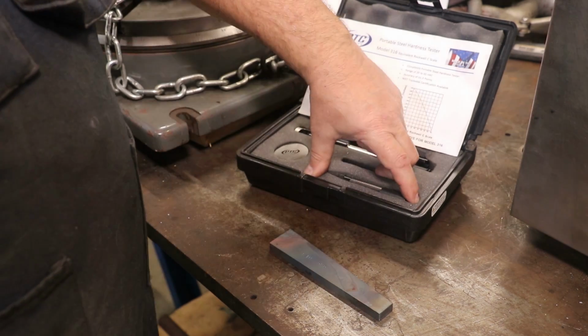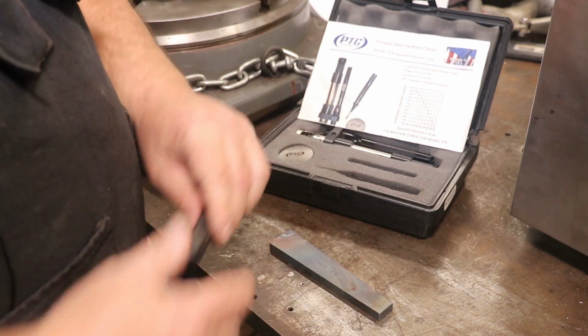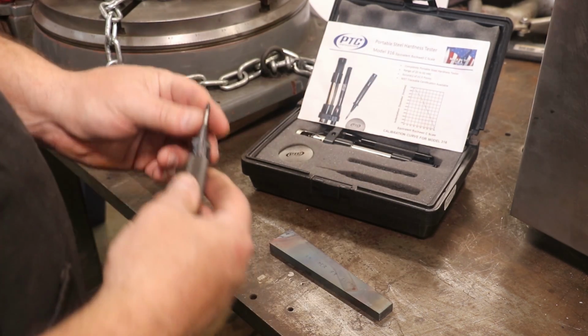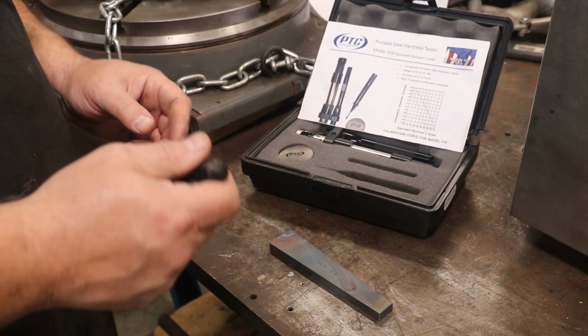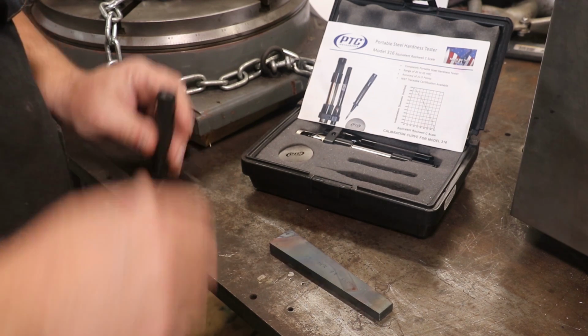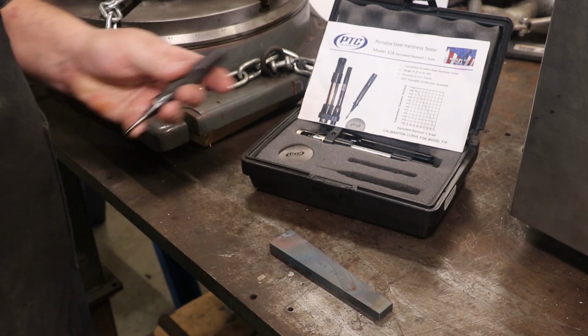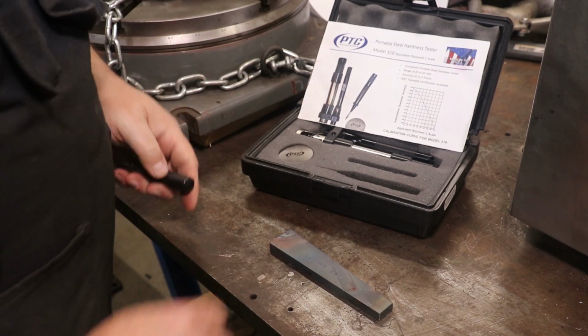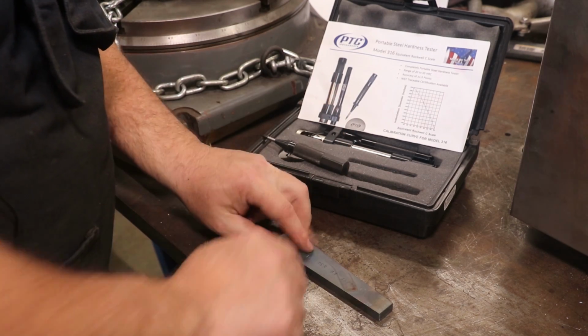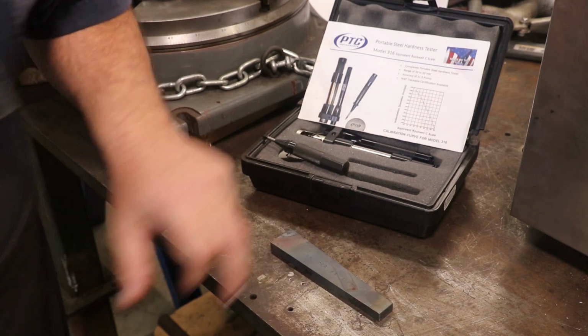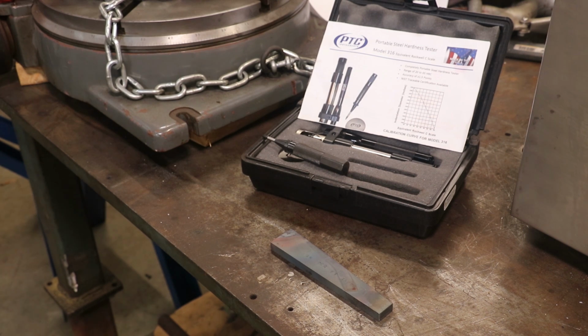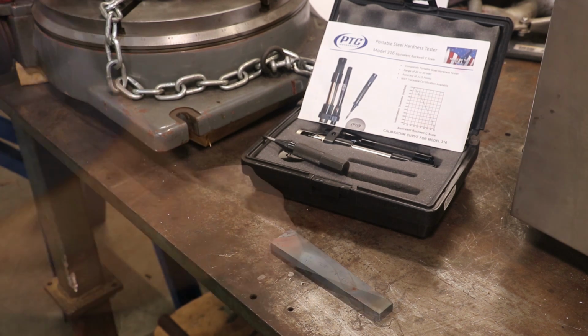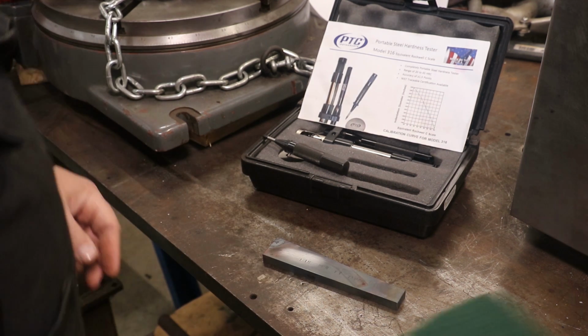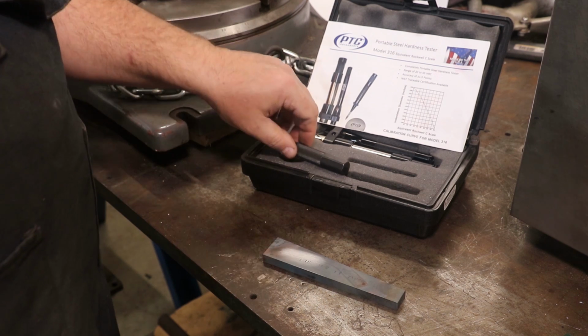This is a fairly simple model. It's accurate to about 1.5 points on the Rockwell C hardness scale. There are much more accurate units out there, but this gives me a good idea where we're at. Pretty straightforward. You want to start by having a nice smooth surface. It's nice to have a shiny surface. I'm going to kind of polish a little area there, just taking a little bit of Scotch-Brite and knocking that oxidation off the surface.